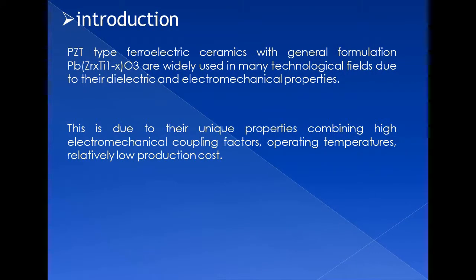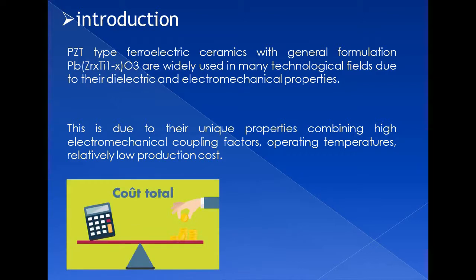PZT type ferroelectric ceramics with this general formulation are widely used in many technological fields due to their dielectric and electromechanical properties. This is due to their unique properties, combining high electromechanical coupling factors, high operating temperatures, and relatively low production cost. It's possible to modulate these properties and obtain specific characteristics for specific applications, precisely by making cationic and anionic substitutions in the crystal lattice of the PZT base material of perovskite structure.